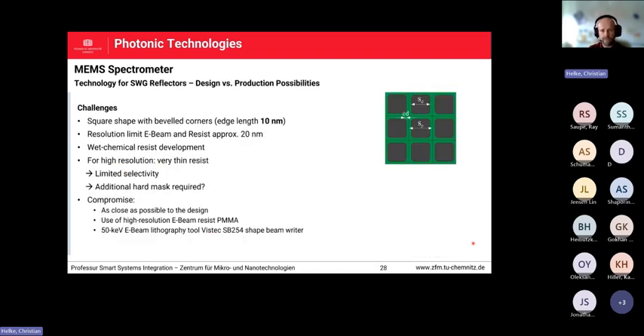For the subwavelength gratings, this design, as I mentioned, consists of 140 nanometer metal patches on 200 nanometer pitch. We used 50 nanometer aluminum on a thin silicon nitride membrane. From the simulation point of view, there was the requirement of these 10 nanometer sharp edges cut away.